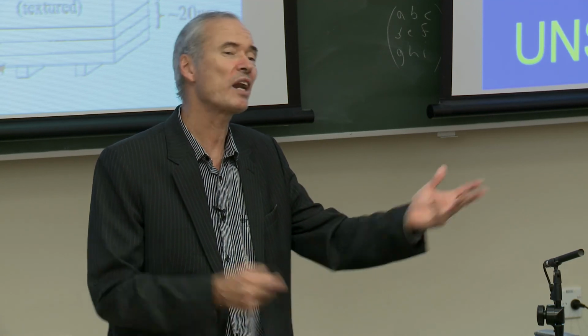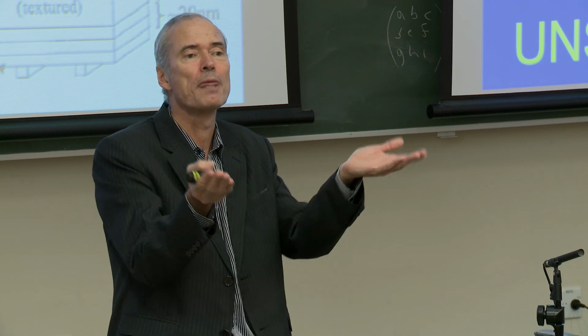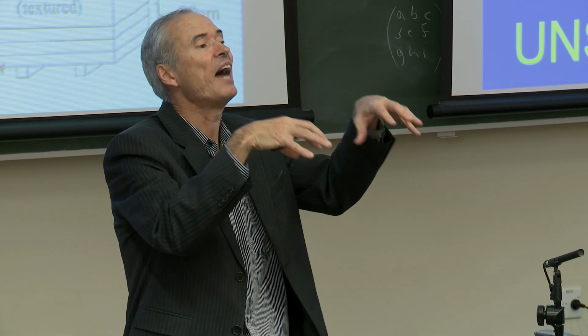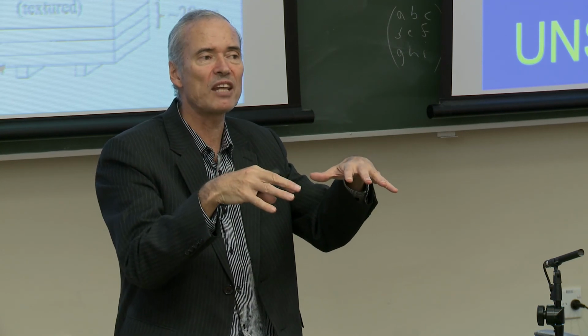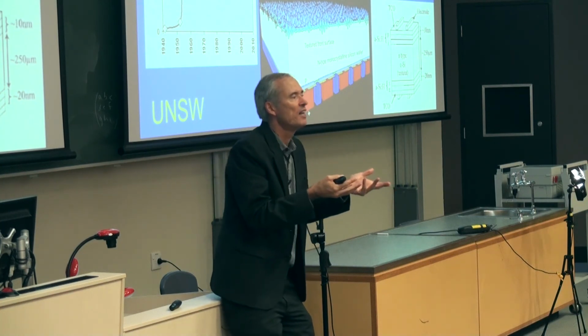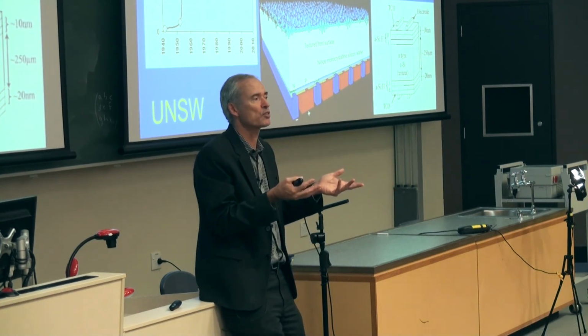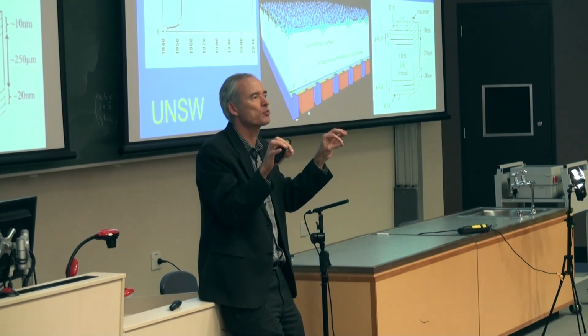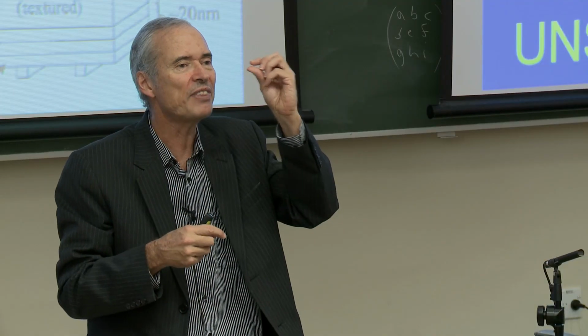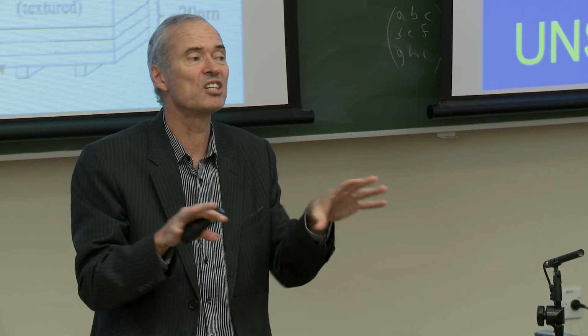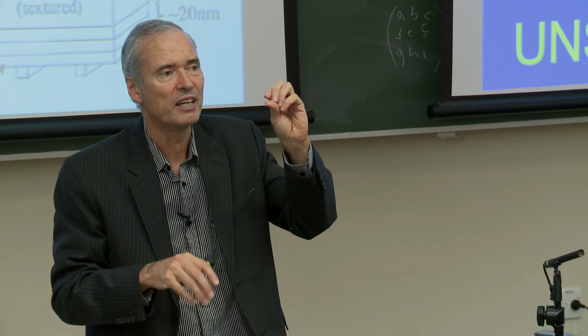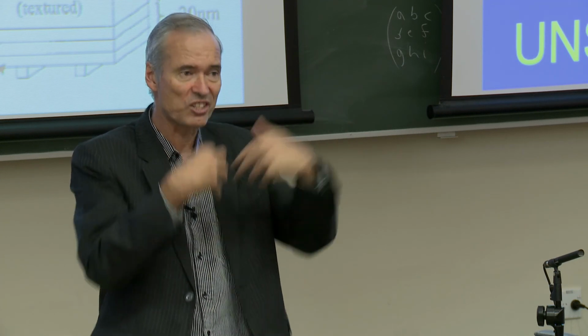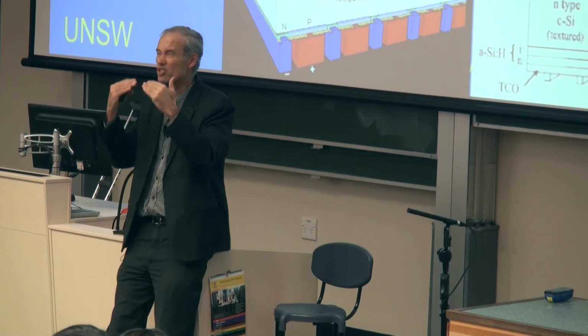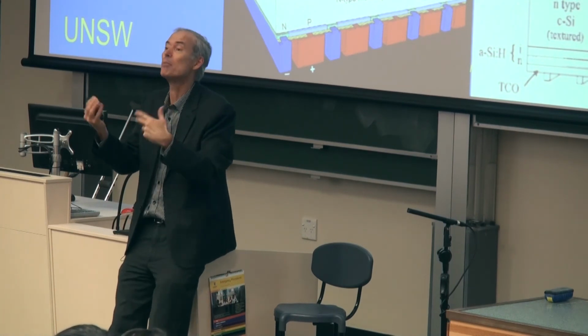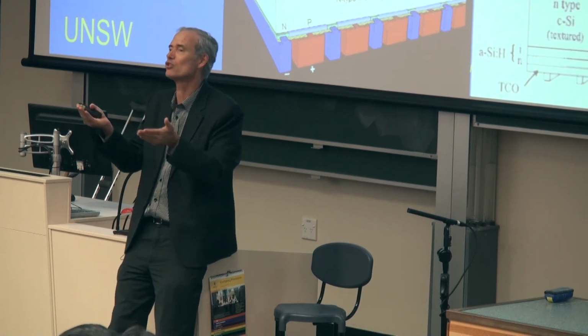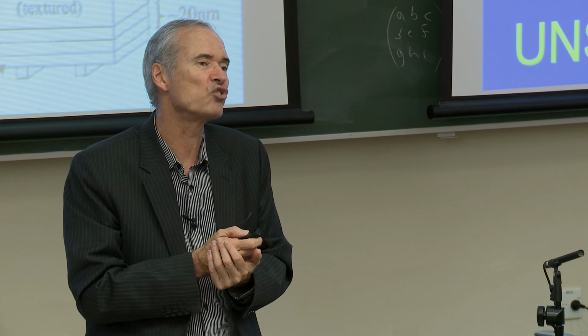Very big difference. And one of the big challenges there is it's a technology where you've got a silicon wafer still, but they use amorphous silicon to passivate the top surface. And there's no doubt that Sanyo has done a brilliant job passivating the surfaces with their amorphous silicon. They do way better than any other technology is able to do at passivating the surfaces. But the trouble is, having an amorphous silicon thin layer on your top surface introduces some big challenges. Because if you get that layer just a little bit too thin, your surface passivation deteriorates badly. If you make it just a little bit too thick, it becomes very absorbing, and a lot of the light doesn't get through to the silicon to be able to generate the electricity. So it's really critical. And you're only talking about a monolayer or 2 of atoms to go from being too thin to too thick. So it's a challenging technology to get right in large-scale manufacturing.